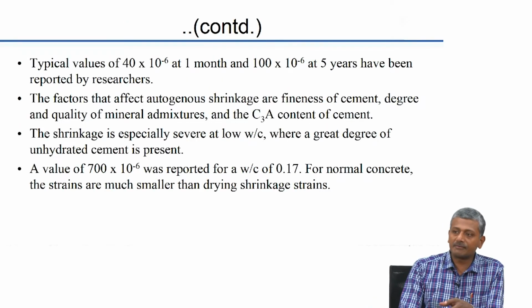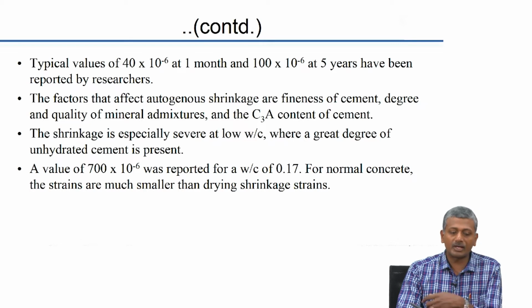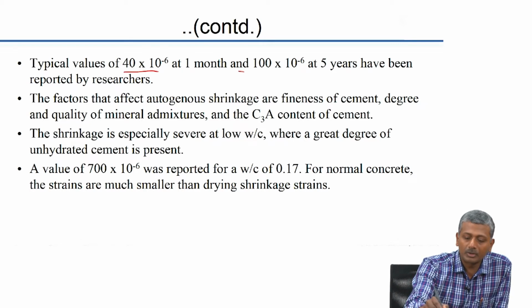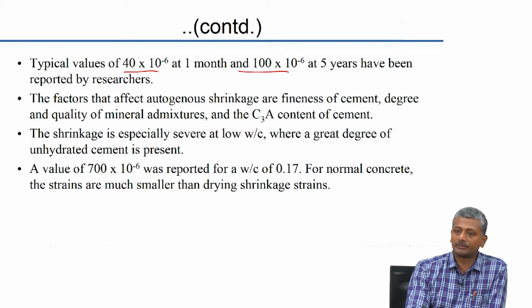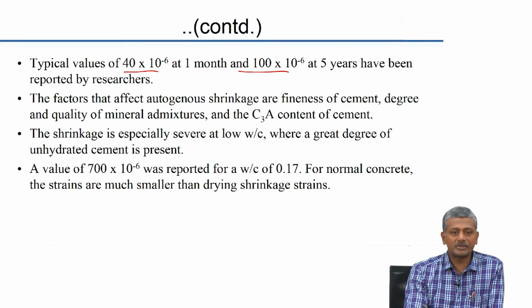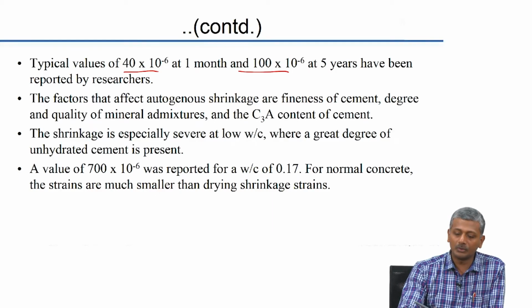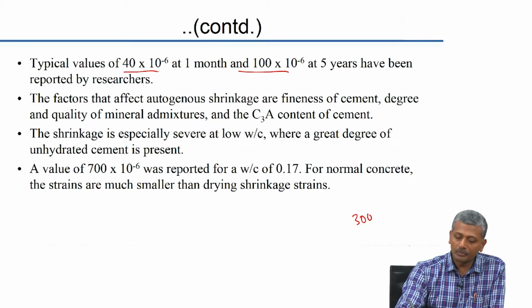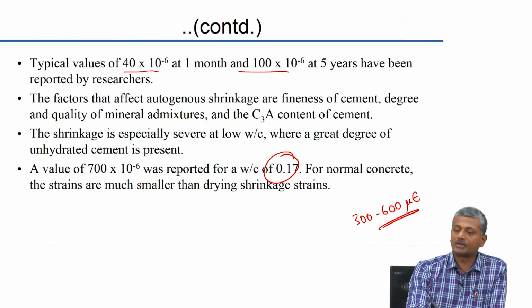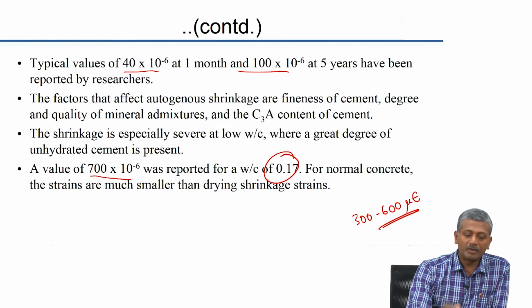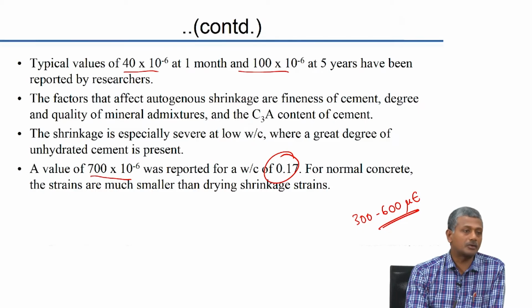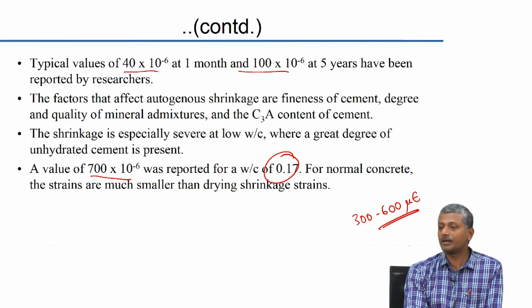Again, several different values for autogenous shrinkage for normal concrete are reported, 40 to 100 microstrains. Okay. 40 to 100 microstrains is very small. What is the typical drying shrinkage value? We are talking about 300 to 600 microstrains for normal concrete. But then when you go for very low water cement ratio systems, people have even reported as high as 700 microstrains. So, that is a significantly large amount of strain that you have in the concrete.